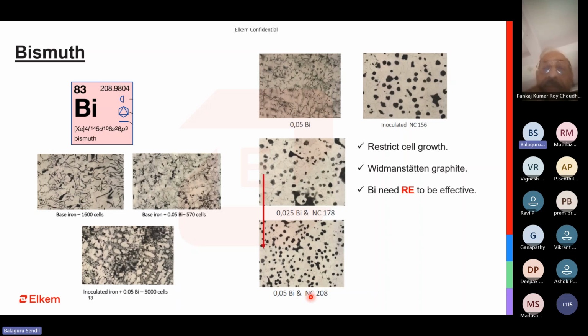What it does is that it definitely needs rare earth to be very effective. Bismuth alone doesn't do anything. So when you are having bismuth coming from your charge mix, this alone cannot do anything. But bismuth combined with rare earth, which is going to be either from your magnesium or your inoculant, or the bismuth based inoculant itself will have rare earth in it. This combination can actually increase your nodule count, can give smaller and better rounded nodules.